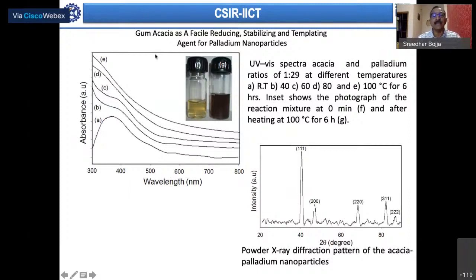As you can see here, initially the color of the solution looked like this at room temperature. We left it overnight but didn't see any difference in color. So we thought of heating at different temperatures like 40, 60, 80, 100 and so on over time. But we could optimize the reaction conditions at 100 degrees centigrade for about 6 hours.